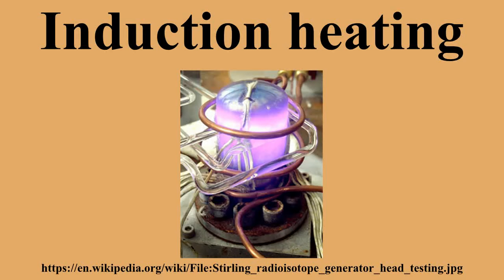Induction furnace. An induction furnace uses induction to heat metal to its melting point. Once molten, the high-frequency magnetic field can also be used to stir the hot metal, which is useful in ensuring that alloying additions are fully mixed into the melt. Most induction furnaces consist of a tube of water-cooled copper rings surrounding a container of refractory material. Induction furnaces are used in most modern foundries as a cleaner method of melting metals than a reverberatory furnace or a cupola. Sizes range from a kilogram of capacity to 100 tons capacity.